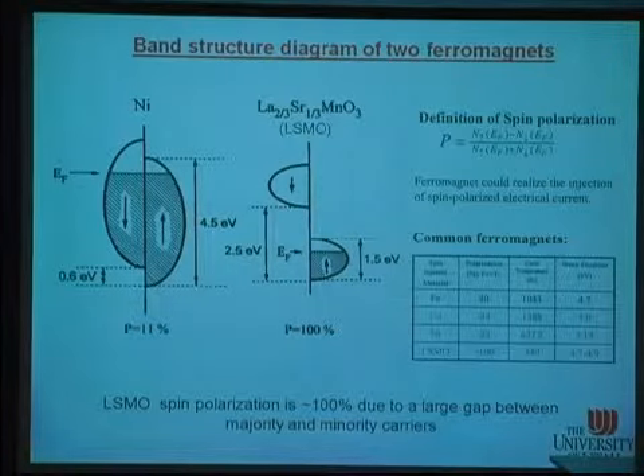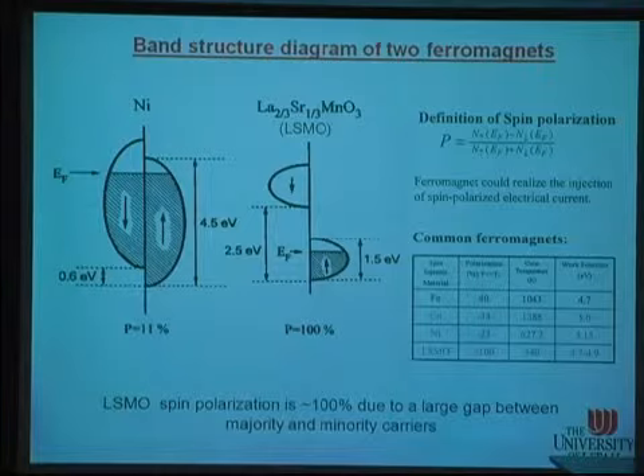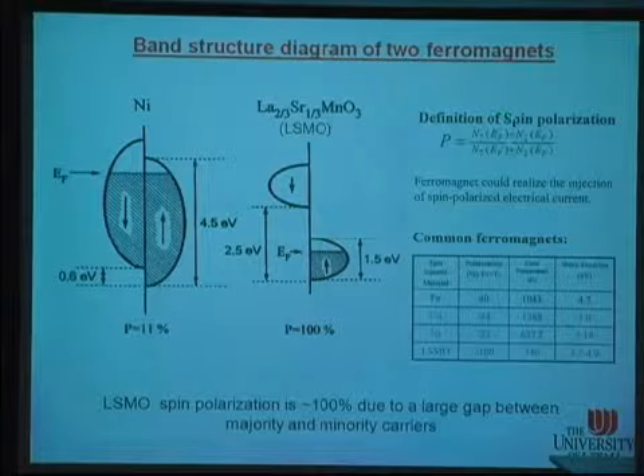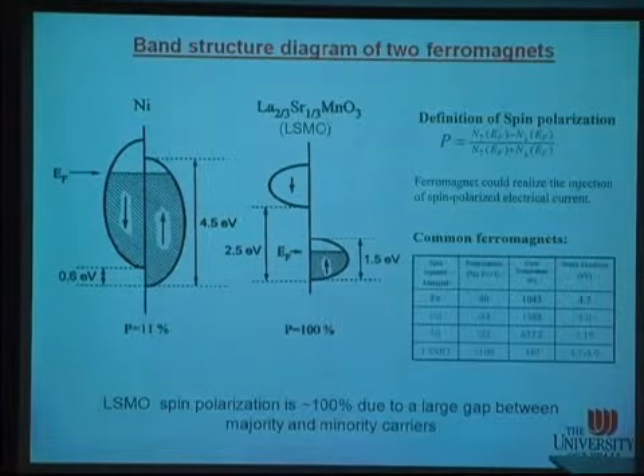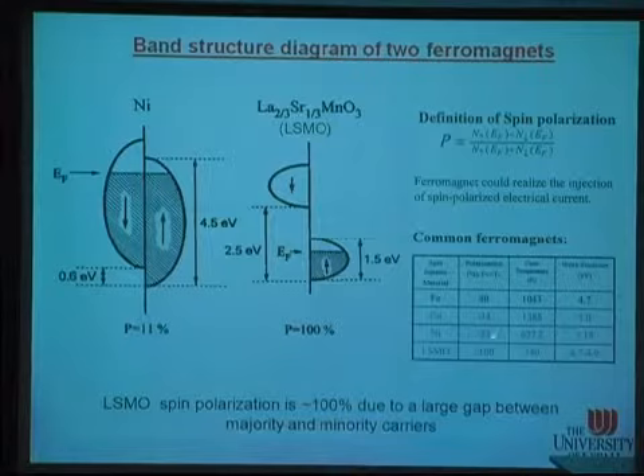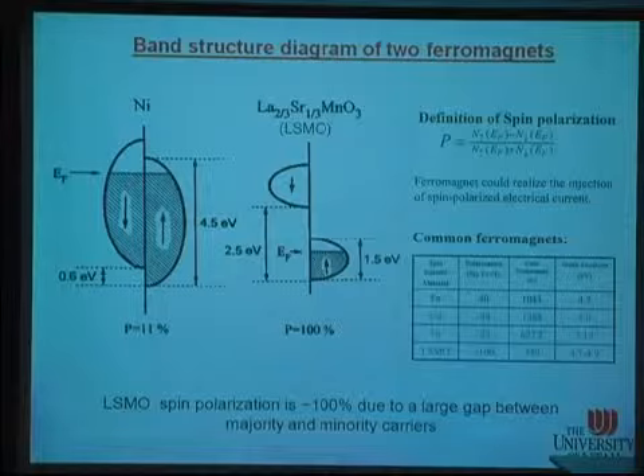Okay, so let's study what the spin polarization is here. The spin polarization is defined by the number of carriers with the spin up minus the number of carriers with the spin down at the Fermi energy. This is very important, at the Fermi energy. And you can see the nickel ferromagnetic material here. The number of the spin down at the Fermi energy is slightly larger than the number of the spin up at the Fermi energy. So you can see the polarization here is minus 23%. This is a small spin polarization material.